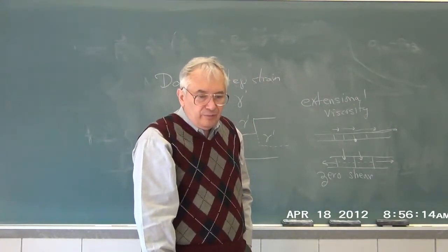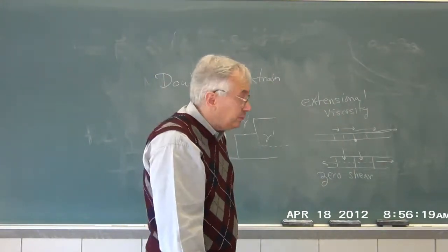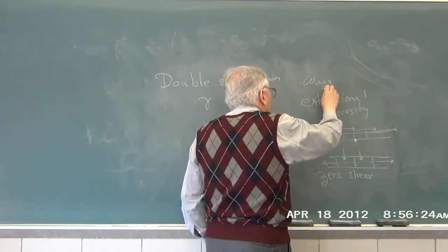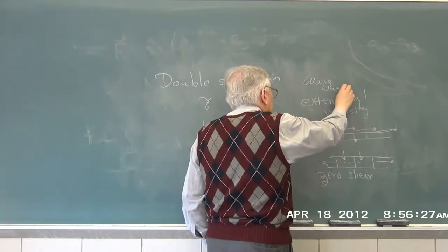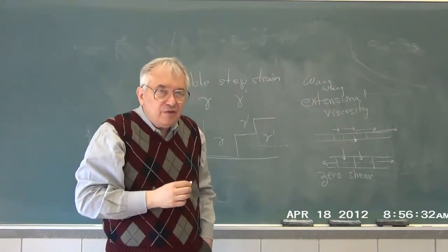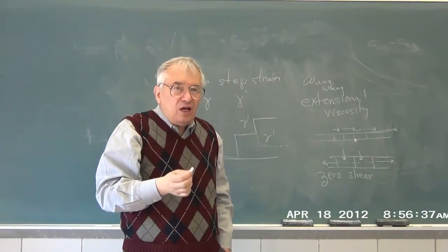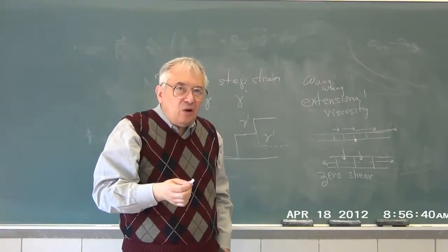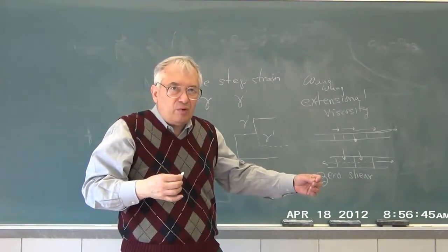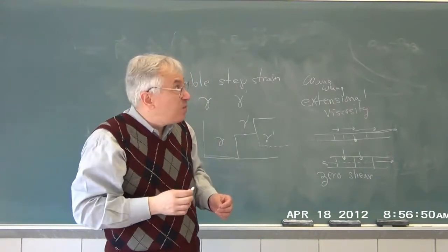There are, however, a series of interesting experiments due to Wang, very nice people. And what they demonstrate is that even if you're extremely careful, you get localized regions where nonlinear things are happening, and the notion that you can just say it's a uniform thread being stretched the same way everywhere along its length at the same time does not hold up to detailed experimental analysis.